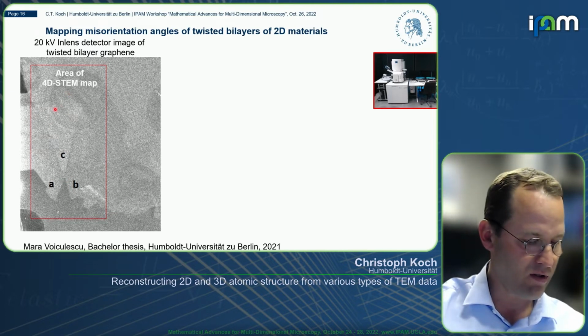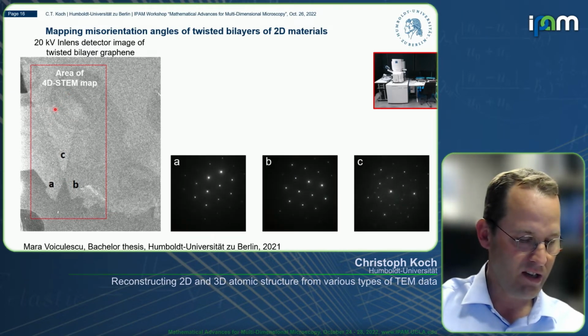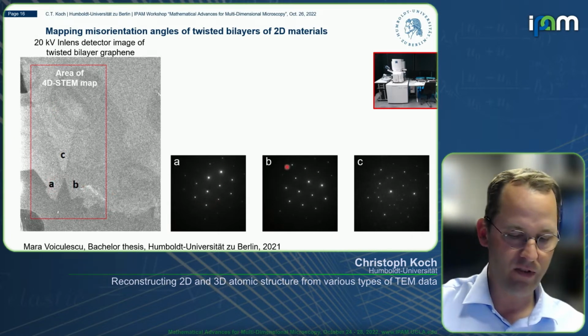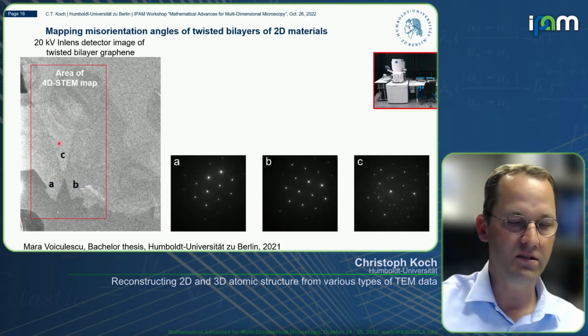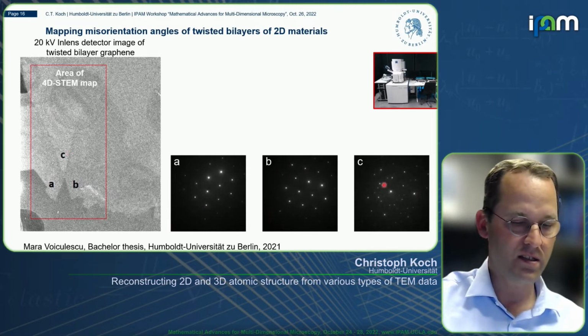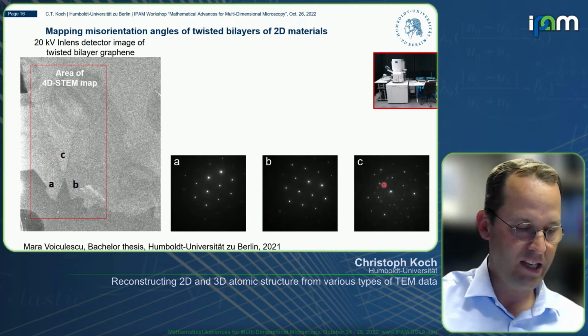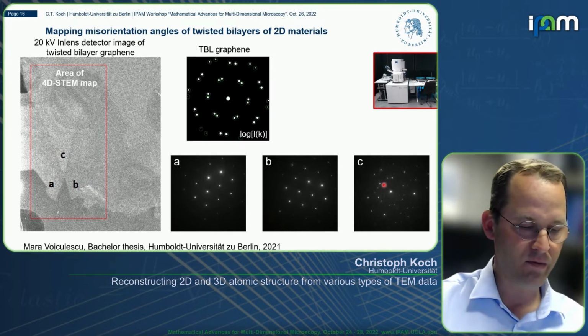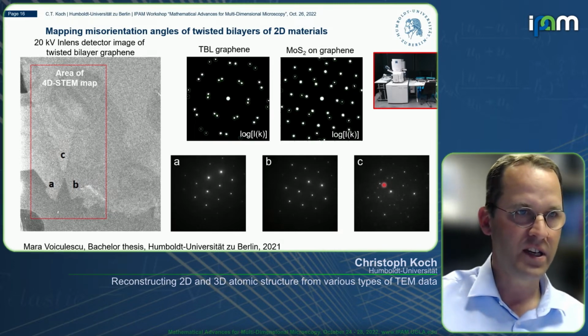And you can see if you record a diffraction pattern from this area, it is a single layer graphene. If you record it from that area here, it's a single layer graphene. And if you record it in the overlap region, you can see the twist angle between the two layers that are superimposed here. And this can be done, of course, also, for example, with MoS2 and graphene or different stacks